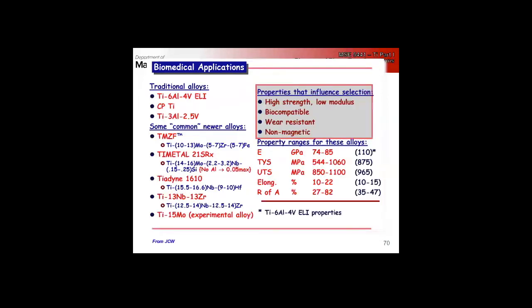Biomedical applications are very important applications. They're biocompatible. Beta is also lower modulus than the alpha alloys. And by clever alloying, you can get even lower modulus. So here's Ti 6-4, Young's modulus of 110. You can get down into the low 70s.